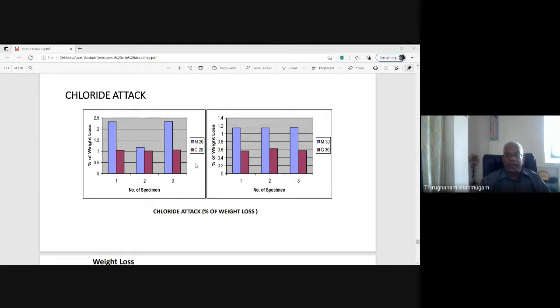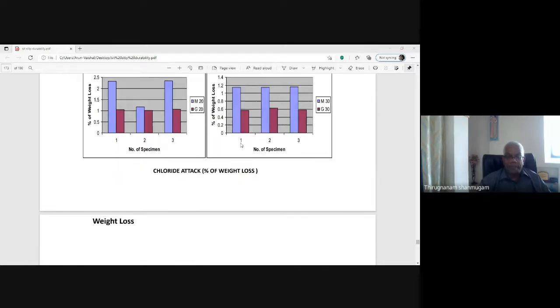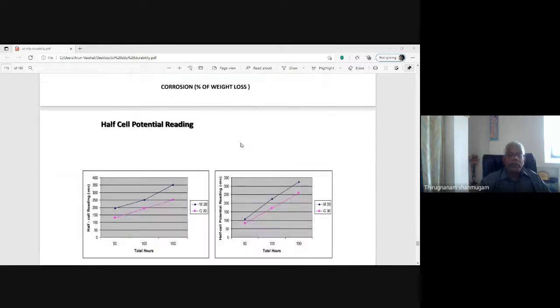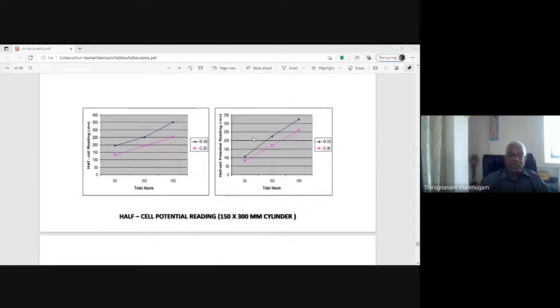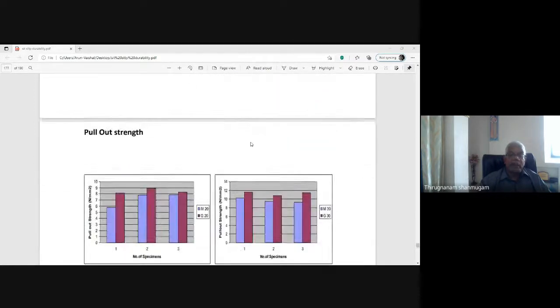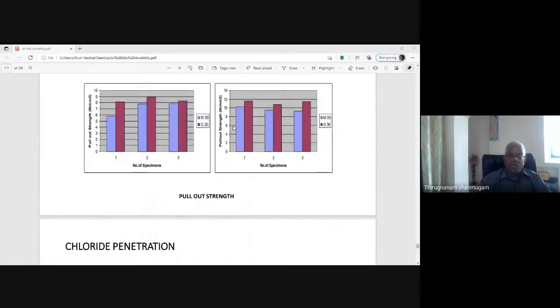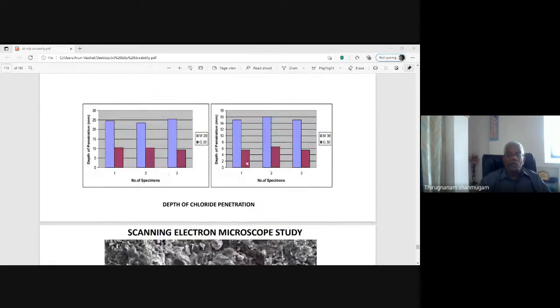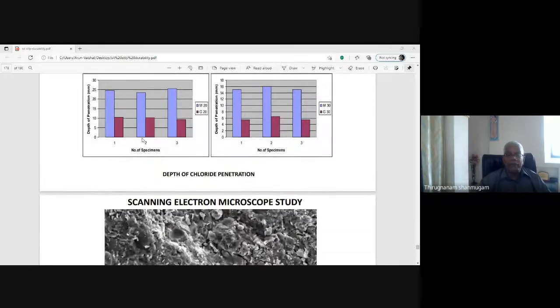M20 concrete and the M30 concrete. In the lower grade concrete, the percentage of weight loss is higher, and here the percentage of weight loss is lower. Half-cell potential reading is also exhibiting the same phenomena. Pull-out strength also indicates that there is not much strength degradation between the admixture concrete and the applied concrete. This chloride penetration is also giving the same results.